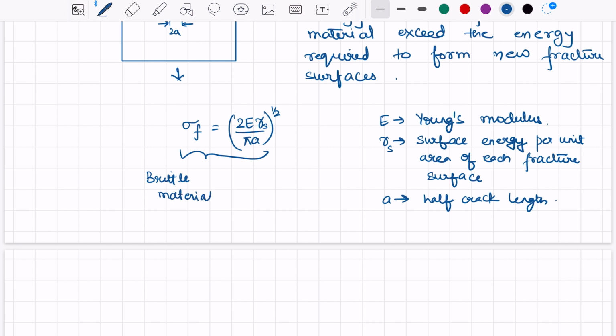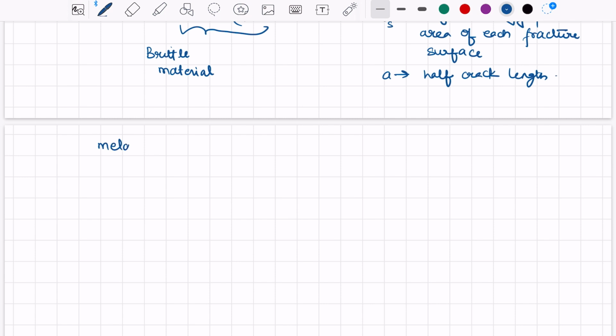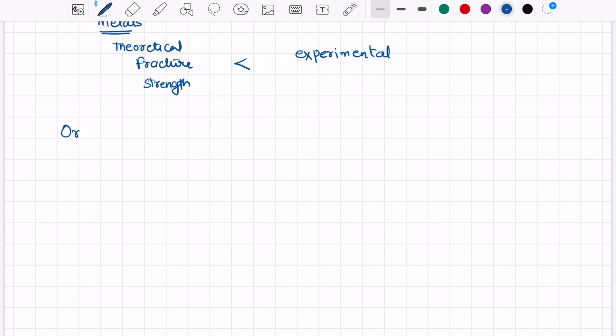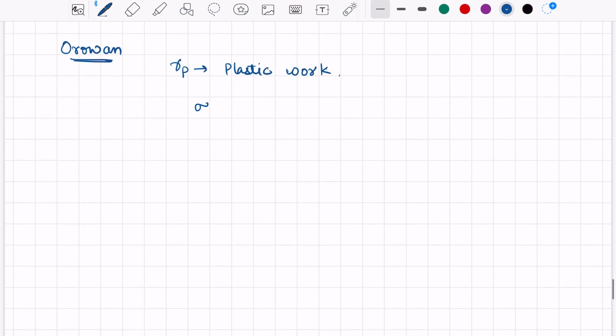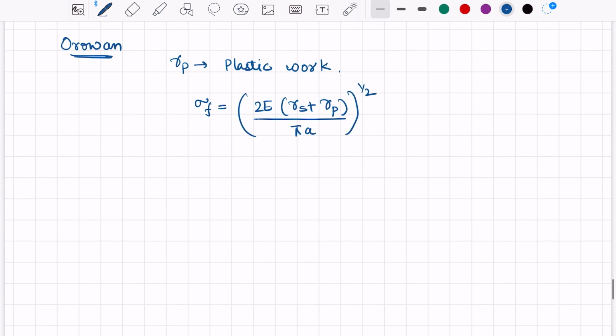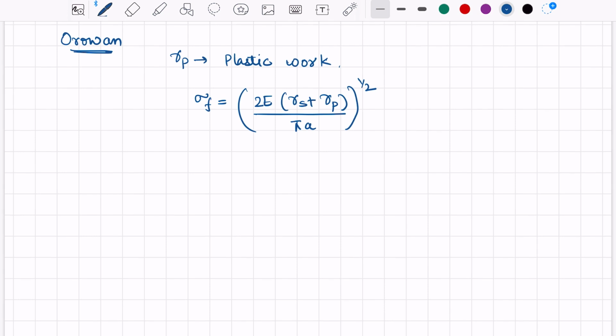However, when the Griffith theory was applied to metals which plastically deform, it was found that the theoretical fracture strength is lower than the experimental value. Orowan then realized that for metals, the plastic work has to be included in the Griffith's equation. For that, he gave the equation as (2E(gamma s plus gamma p) / pi a) to the power half. He included the plastic work in the Griffith's equation, and by this addition, the experimental value and theoretical value finally came in agreement.